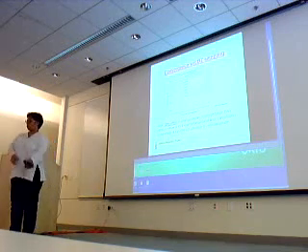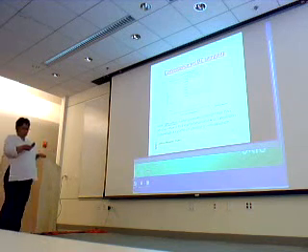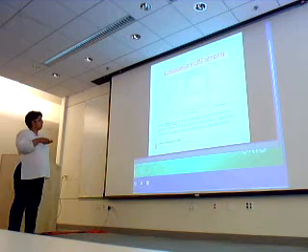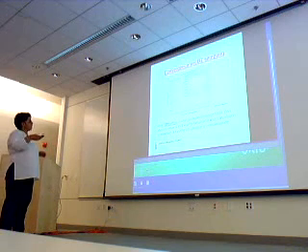So when you're running a code, you have to check that you're converged with respect to your choice of K points. So here is an example. This was one of my students, she just ran it. So she took carbon in the diamond structure, and this is the total energy as a function of the number of divisions she chose in her K-point mesh. And you can see that here it looks like it's converging, but the scale is a bit difficult to see, so she blew it up here.